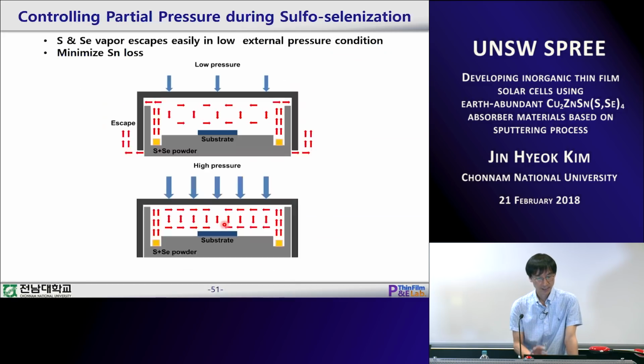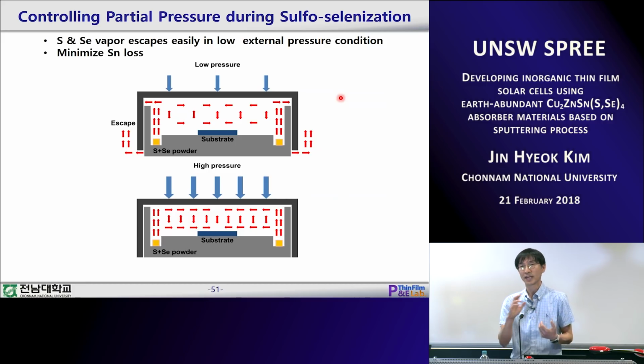Okay, and the third one is the partial pressure control during the sulfo-selenization process. There are many chances for sulfur and selenium evaporation and tin loss during the sulfo-selenization process, because the graphite box lid is not fully fixed. If there is room here, it is easy for these gases to escape to the chamber. That means the atmosphere in this graphite box will differ depending on outside pressure. So we tried to change the outside pressure to see the difference between low and high outside pressure.